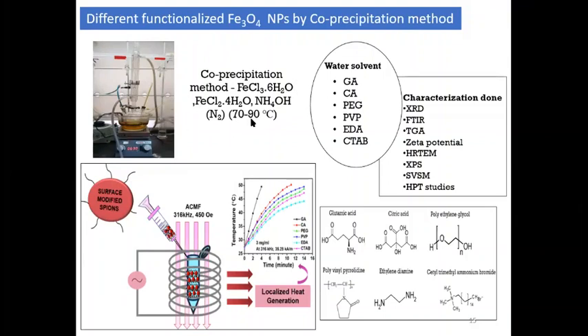In the co-precipitation method, you use a solvent like water, or sometimes ethanol or water-ethanol mixtures, and you can use a base like ammonia, ammonium hydroxide, or sodium hydroxide, or an acetate like sodium acetate. The material has to be synthesized under a nitrogen atmosphere to control the proper oxidation and to form the iron oxide nanomaterials. We have used chloride salts, FeCl3 for the 3+ ions. As most of you are aware, iron oxide has +3 and +2 charges in the structure. It is an inverse spinel structure, so we must use the +3 as well as +2 in the proper stoichiometric ratio.